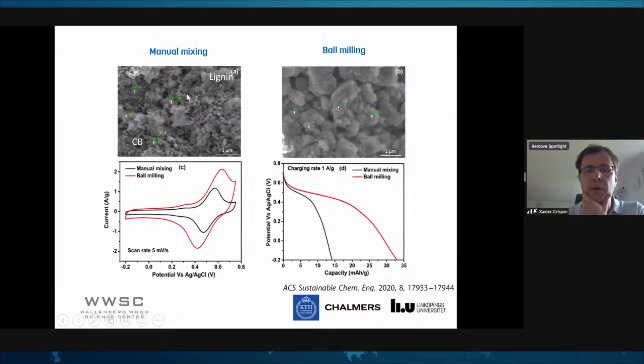For instance, here in materials, you see this is a manual mixing. It's a SEM image where you see two types of phase, a bit a light color with a large particle, which is lignin, and then you have a darker color with very, very small nanoparticles, which are the carbon. So by just manual mixing, it's extremely difficult to get a good material. And then you have still the two phases. You are not mixing intimately those materials well enough.